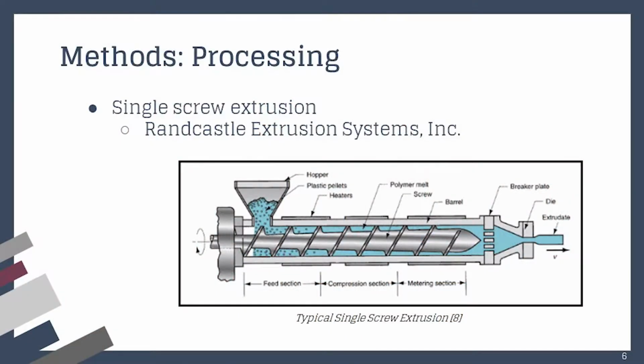So the different compositions, the 7 different ones that we used, were made by the Randcastle company, and they use a single screw extrusion method. And so how this works is they put the raw forms of polystyrene and HDPE into the funnel of the extruder, and then the plastics move in and they're combined. And as they move along, there's heaters that raise the plastic mix to a certain temperature. And as they move through this screw as well, there's a high shearing process that occurs.